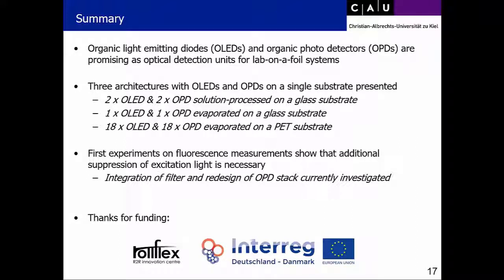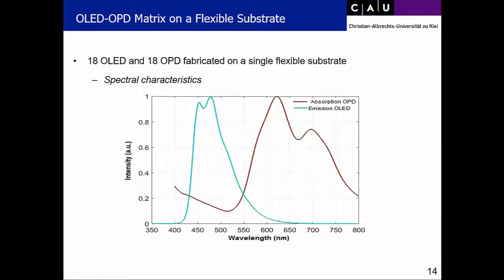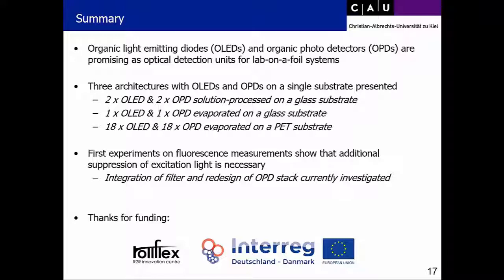We did do first fluorescence measurements. As I already said, we don't have enough suppression of the excitation light because we do have some spectral overlap in this region here. So currently we are pursuing two redesign routes. One is to add an additional filter in the system. The other is to redesign the OPD stack, which in principle is also possible in order to get a more narrow absorption, such that we do not have the direct excitation light. Since for fluorescence detection you need to have orders of magnitude, basically, suppression of the excitation light.